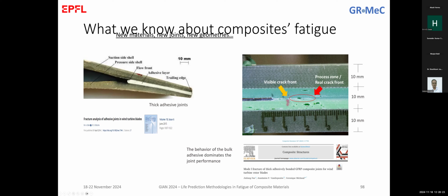We've seen a lot of voids in the material. We've seen the crack deviating from the midplane, and all these are components that have been overlooked in the past, not necessarily because people didn't care about this, but because they were not involved in the fatigue failure of other types of structural components. So now with these new materials that we are investigating and introducing in structures, we are also opening new ways for research in this case.